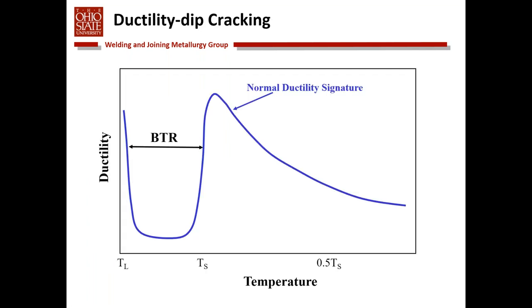Okay, I want to spend just a few minutes here talking about ductility dip cracking and a Gleeble-based test that we've developed to evaluate DDC. So what is DDC? As I showed previously, a normal ductility signature tends to look something like this. A material that's susceptible to ductility dip cracking shows a sudden dip in ductility, typically above about half the solidus temperatures of materials. And so in stainless steels and nickel-based alloys, this temperature range tends to run from about 800 to 1100 degrees centigrade.